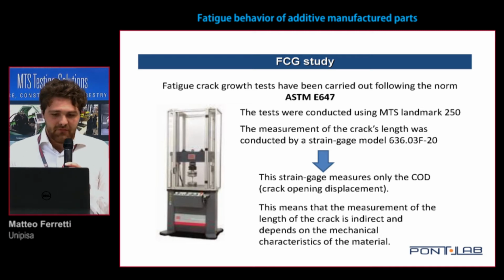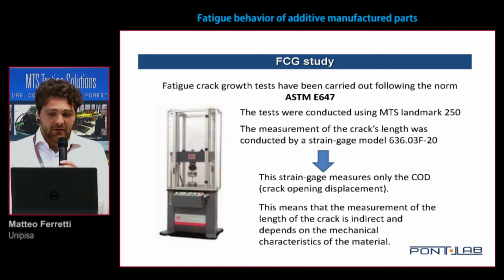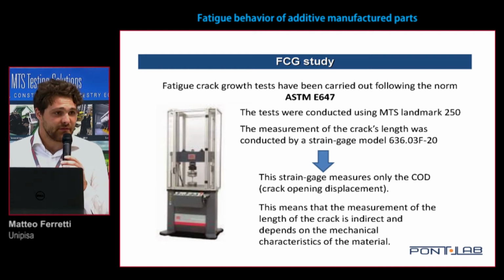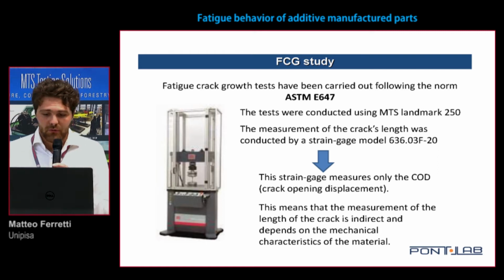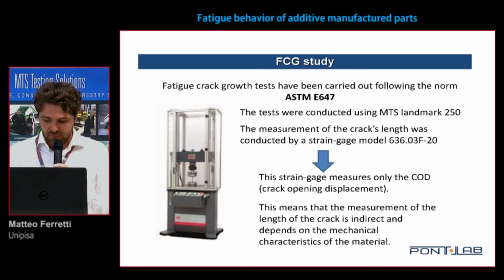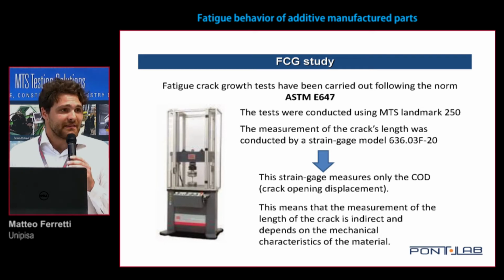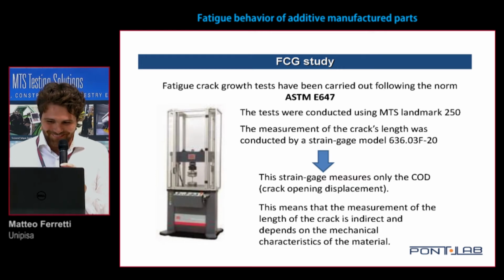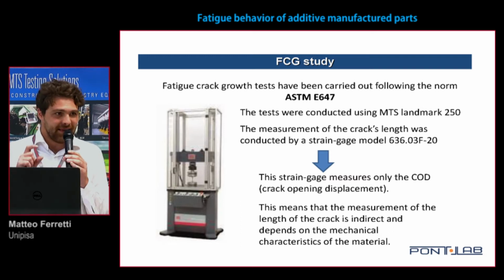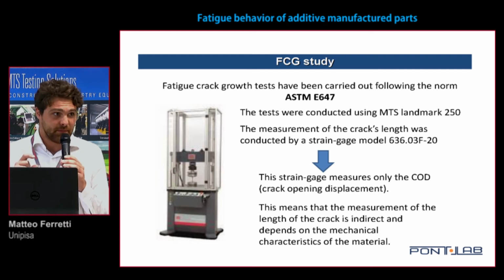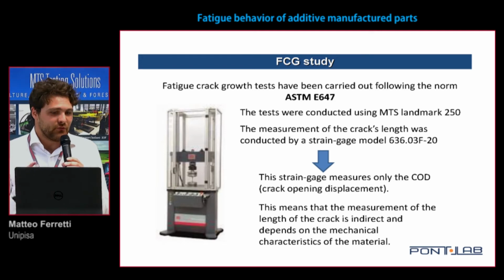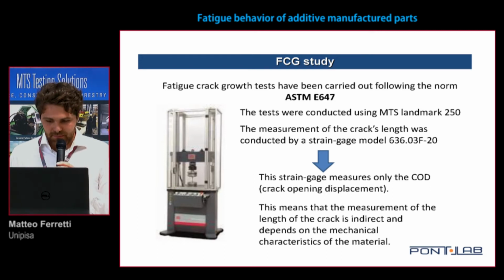The study is a fatigue crack growth test that is being carried out following the norm ASTM E647. The tests were conducted using an MTS machine Landmark 250, and the measurement of the crack length was conducted by a strain gauge with this model. The strain gauge, in particular, measures only the COD. COD is the crack opening displacement, the distance between 2 points over the specimen. This means that the measurement of the length is indirect and depends on the mechanical characteristics of the material.